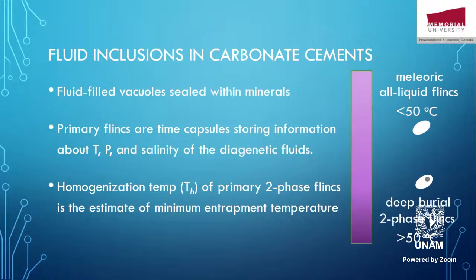The primary fluid inclusions are like time capsules storing information about the temperature, the pressure, and the salinity of the diagenetic fluids. The homogenization temperature of the primary two-phase fluid inclusions is an estimate of the minimum entrapment temperature of that cement. Of course, in the carbonate cements you will find two types of fluid inclusions: all-liquid inclusions, which are formed at or near surface temperature, below 50 Celsius, or two-phase fluid inclusions, a fluid with a vapor bubble inside, which are formed at temperatures higher than 50 or 60 degrees in deep burial settings.